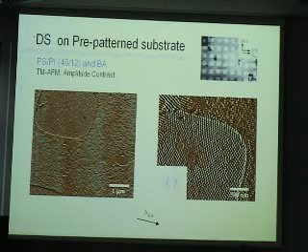If you look inside this area, as we expect, in the matrix region the cylinders are oriented along the B-axis of benzoic acid, directionally phase separated. And on the mountain region, the cylinders are hexagonally packed and standing up due to the thickness variation.